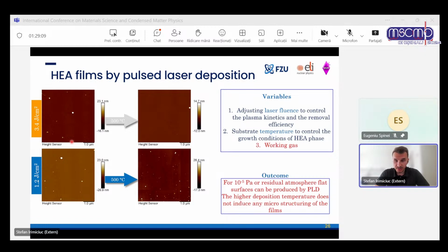I'm getting closer to the end. I don't know how much time I have, maybe 5-10 minutes, but now we're talking about high entropy alloys. So we did a quick test for high entropy, and we tried two different fluences. Different fluences mean different energies in the plasma for the ions as they help the growth. And then we also tried different temperatures to see which would be an optimum temperature for these films.